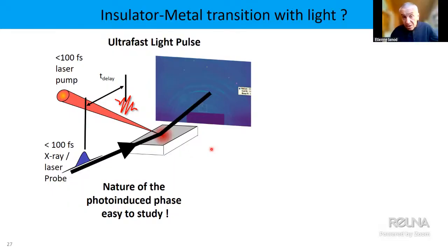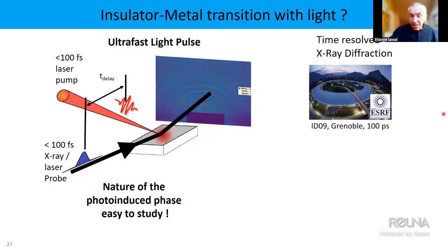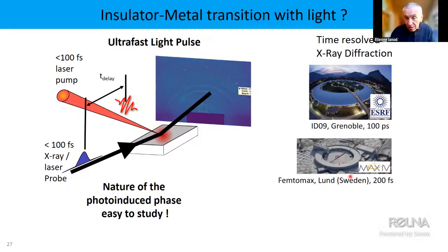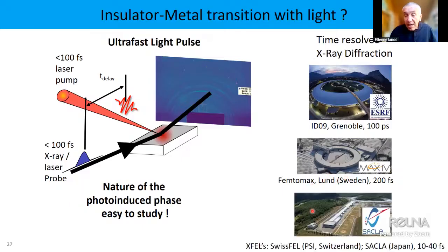And we can study the evolution of the electronic properties, if we do pump-probe in optical reflectivity, but we can also probe the structural evolution with a time resolution which is way below the picosecond. And that's what we have done in many places to study this structural evolution. So we have done time-resolved X-ray diffraction at the European synchrotron in Grenoble, but also in Sweden on the FemtoMAX beamline, and as well in Japan. Here is a picture of the Japanese X-FEL called SACLA. All right.